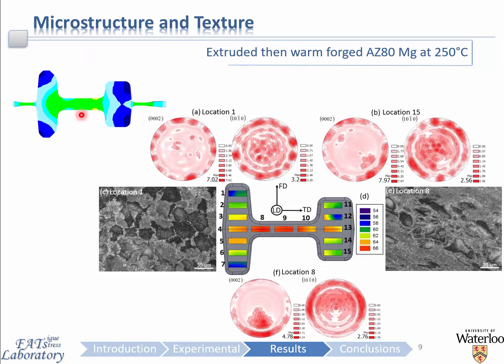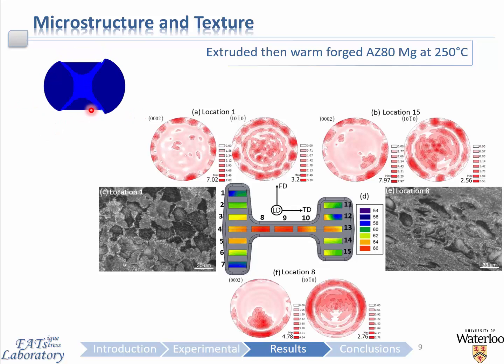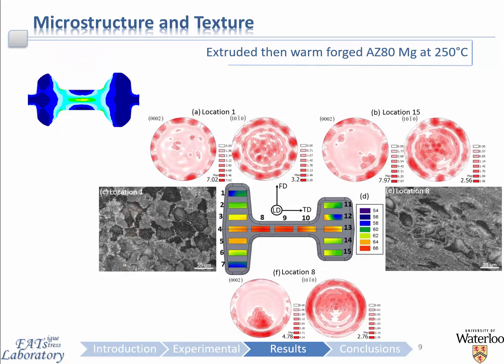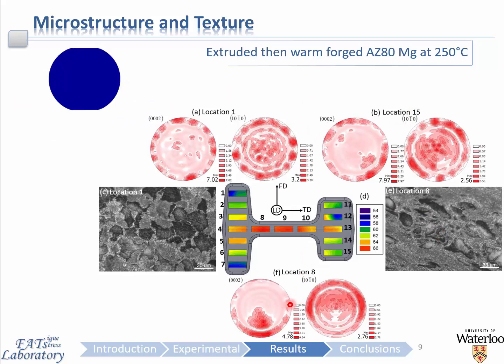Following warm forging, the microstructure is effectively frozen, preserving the texture. However, the warm temperature and slow cooling rate are enough to annihilate any of the residual twins which remain, meaning that the microstructure that's observed of the forged material is virtually free of twins and has a local texture that varies throughout the cross-section of the forging, as illustrated here.